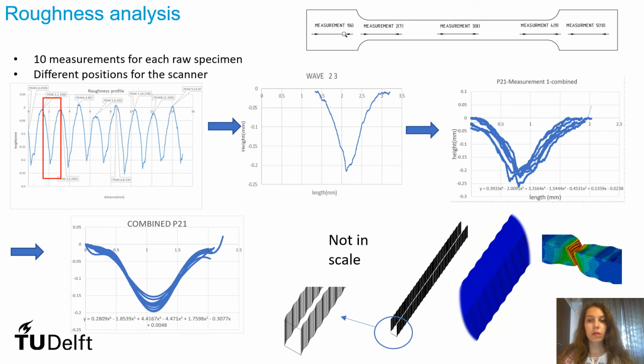From these measurements that were made with different positions for the scanner, I extracted firstly a roughness profile with the height of the roughness and the length of the measurement. I extracted each wave from the roughness profile and put them together, shifted them to 0, and extracted a 6-degree polynomial that best describes the roughness for just one measurement of one specimen.